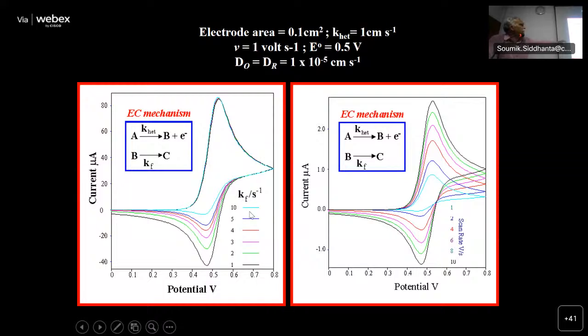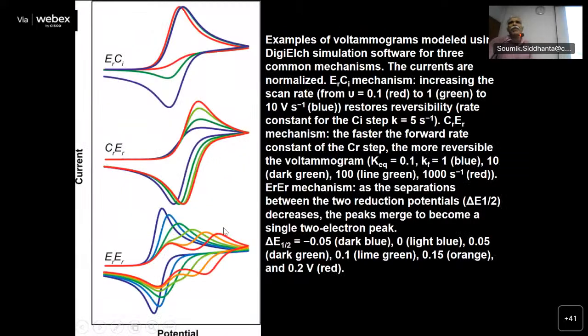Accordingly, you will get different shape of voltammogram. So you see here, Kf per second is the rate constant of the chemical reaction. So at 10, 5, as you change the rate constant, voltammogram undergoes a change in the shape. From that, you can predict whether the reaction is coupled with chemically or not. Typical example, ErCi. Er means reversible electron transfer, irreversible chemical reaction. This is what you expect with the variation of scan rate. CrEr, chemical reaction is reversible, electrochemical also is reversible. You see, not much change. ErEr, 2 electron transfers followed. Some case you get 1 peak, some case you get 2 peaks. So the difference between these peaks, the irreversible Er1 and Er2 also can be analyzed by changing scan rate. So please remember the scan rate variation of these will allow you to understand the mechanism.